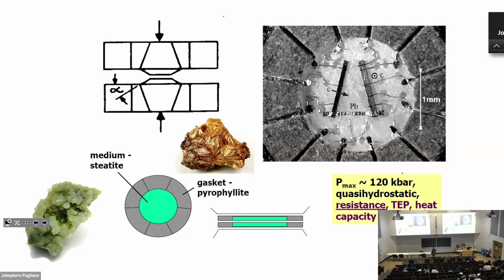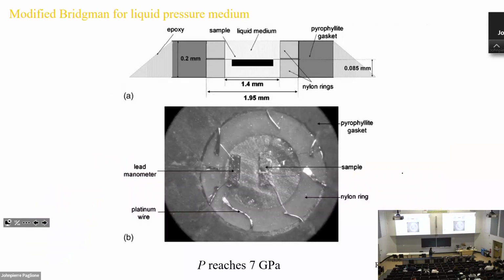So people have been thinking, can we include a liquid medium? At the time, there were a few other papers also. This is from Grenoble. The idea is you use two layers of gasket. The outer layer is still this pyrophyllite, and inside this gasket, you use this nylon. Nylon is soft. Once you squeeze, you cut some hole, and the electrical leads come out of this hole. Once you squeeze, the hole will get closed, and if you have liquid there, the liquid will stay. With this type of thing, you can still get to 7 GPa.